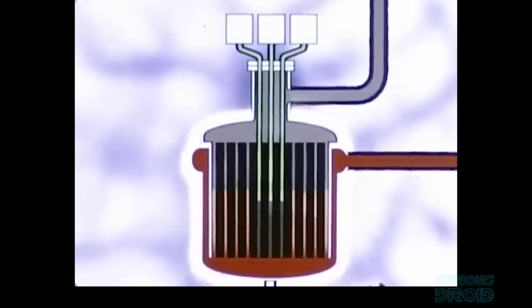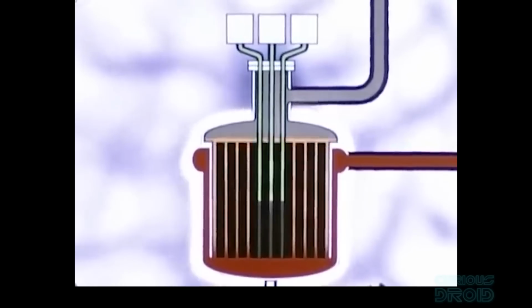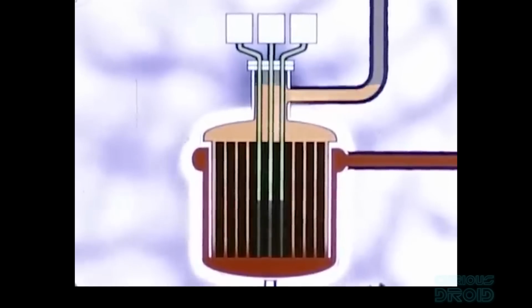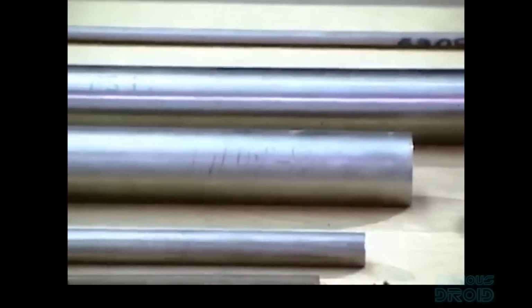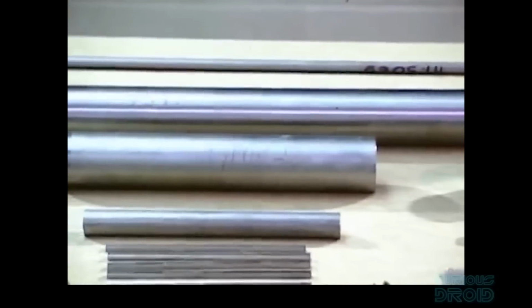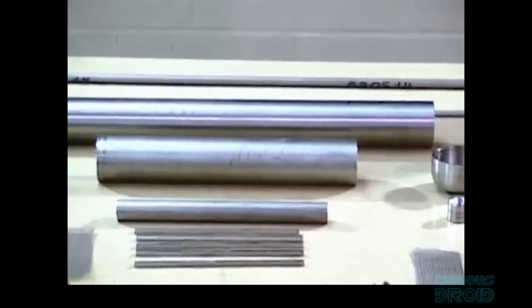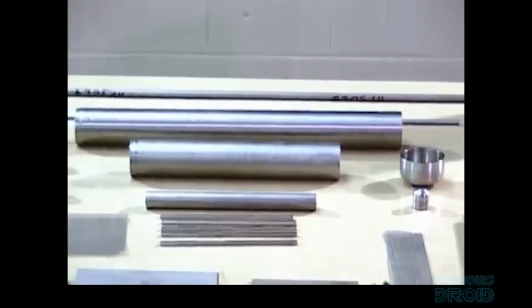So it was not possible to induce a meltdown. This is the core primary safety feature of a molten salt reactor, and the one which differentiates it from a traditional water-cooled reactor. However, after the reactor was shut down, there was found to be a problem with the corrosiveness of the salt and the hastelloy alloy which was used to create the structure.